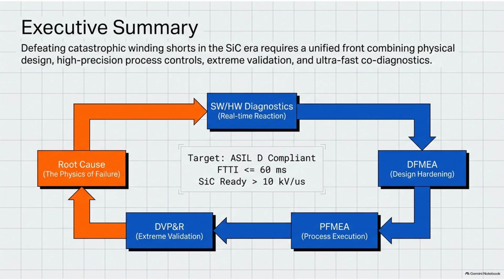Right, because the wires aren't just bare metal. No, the copper wires in the stator aren't wrapped in thick plastic like a household extension cord. They are coated in a microscopic layer of paint-like polymer enamel. And under constant extreme thermal stress, the long molecular chains in that polymer begin to break down. The enamel undergoes irreversible thermal aging. It gets old fast. It loses its flexibility, becomes brittle, and its dielectric strength, which is its ability to block electrical current, massively degrades. Okay, so the foundation is weakened by heat.